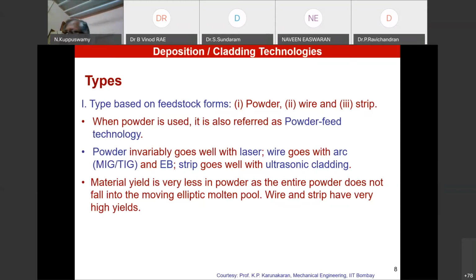But wire is preferred because a typical wire costs you, for instance, for titanium, about $45 to $50 a kilo, whereas powder for titanium, for instance, costs you $200 a kilo. Therefore, it's a huge difference in price. But of course, most of the people prefer powder bed.